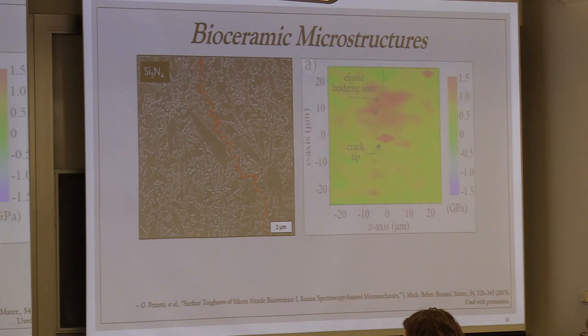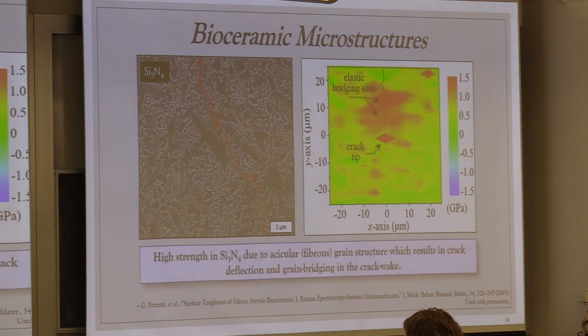And you can see that in this particular stress analysis, which shows that there are compressive stresses around the wake of the crack as it proceeds through the material and at the crack tip, because you have these bridging grains and you also have deflection that occurs. And this is what gives silicon nitride its strength and toughness. Now, the interesting thing here, and what I have to point out, is this is a mechanical-based toughening mechanism, as opposed to the zirconia material, which is a chemical phase-based toughening mechanism.